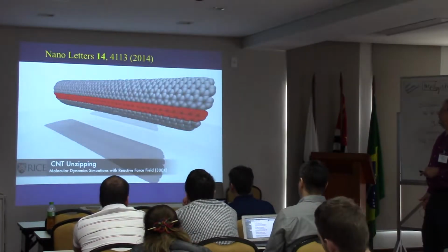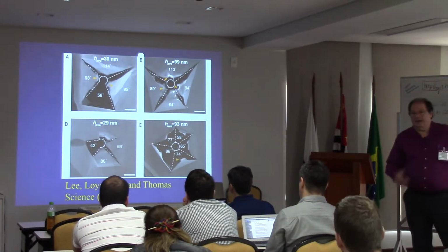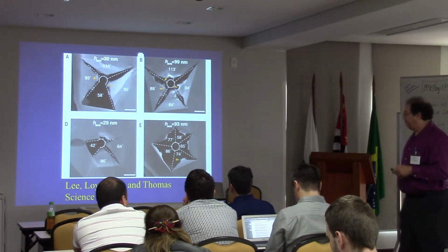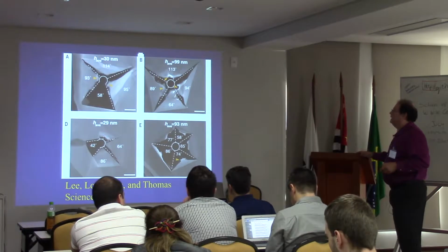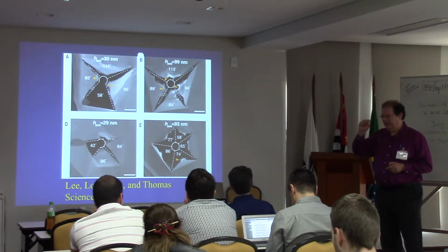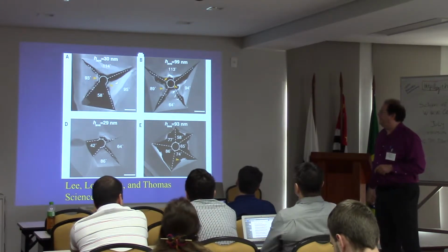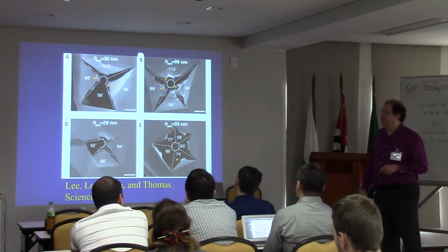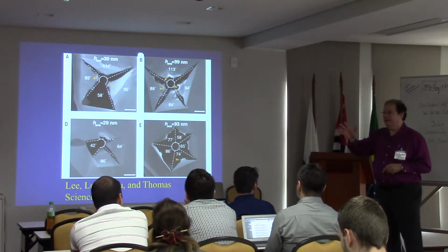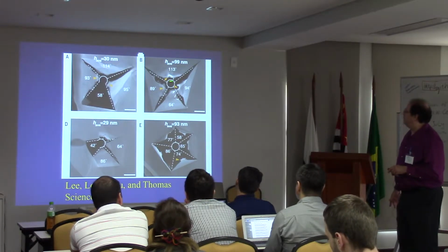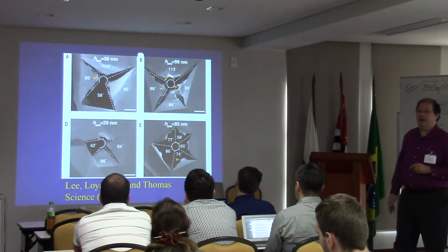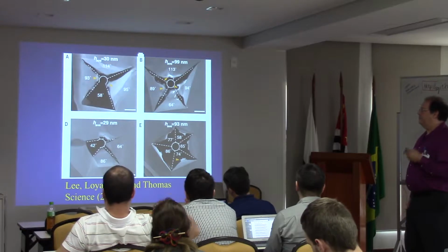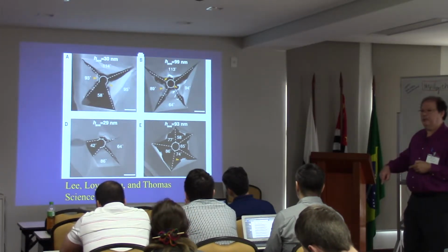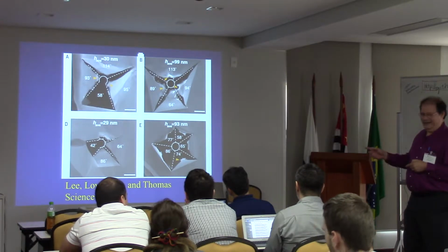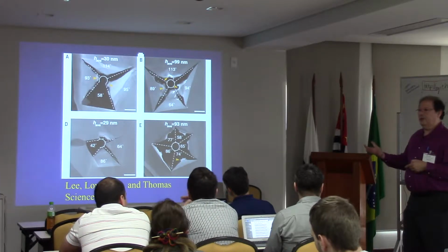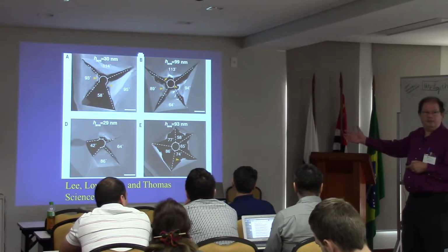So I go fast. Here, Pedro already talked about this. But fracture at the nanoscale is a very hot topic again. This is a paper published a couple of years ago by another group from Rice, where they shoot silicon nanoparticles against graphene layers and see how it breaks. To their surprise, it's like a bullet into a wall. The fracture is very unique. It only breaks forming these petals, and these petals have very specific angles. The question is why they break forming these very unique patterns. Again, from the experimental point of view, they cannot follow it, it's too fast, and they cannot have enough structural data to follow the process. Only simulation can help to explain this.